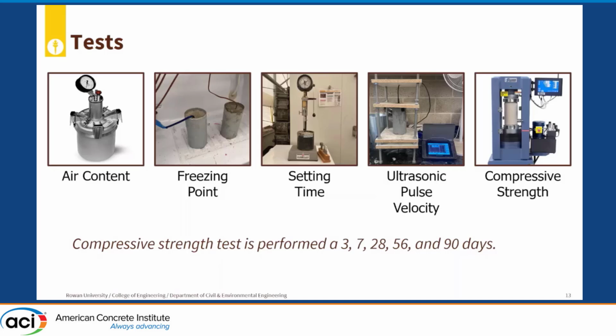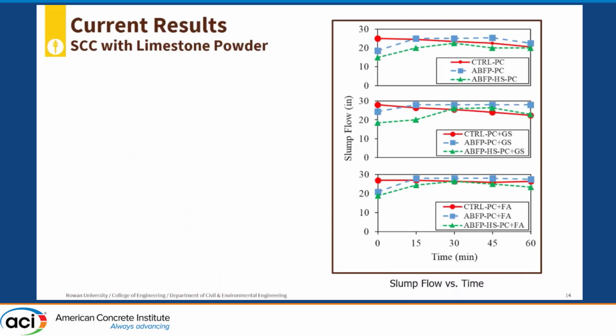A standard method for measuring setting time is the penetration resistance test. However, we find this somewhat impractical, especially for doing it under cold temperatures. So we also explored using ultrasonic pulse velocity, or UPV, to predict initial and final setting times. We have a poster this afternoon for the relationship of these two tests. My current results revolve around SCC with limestone powder only.